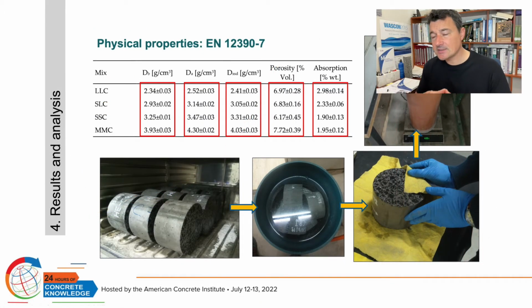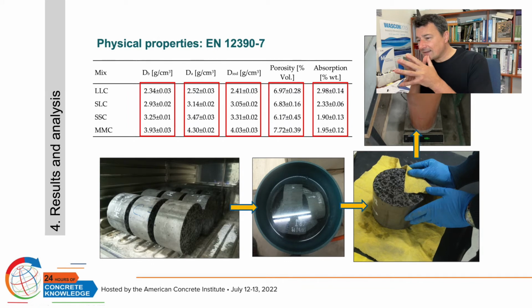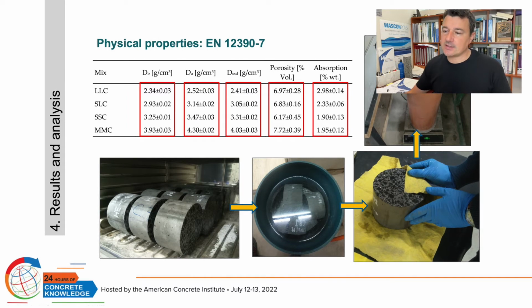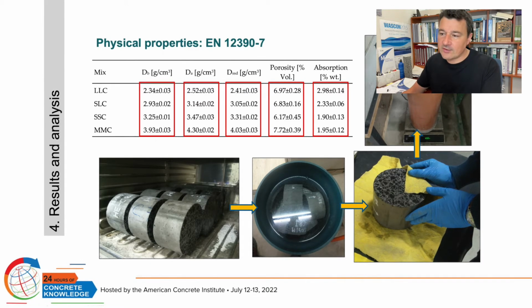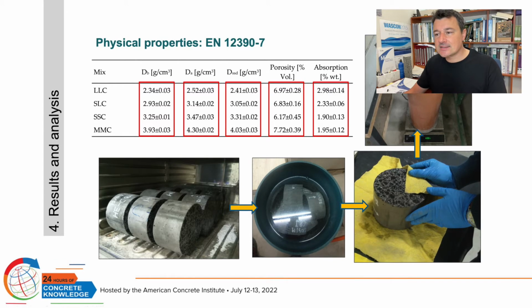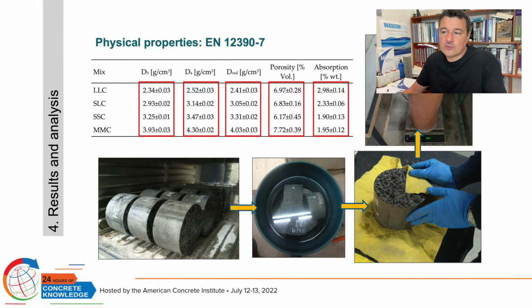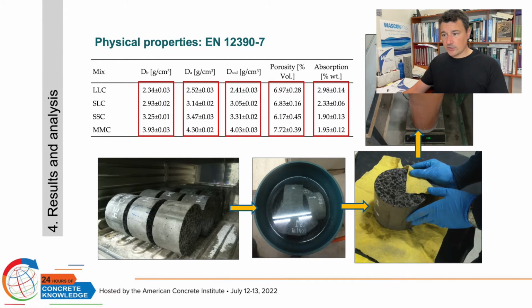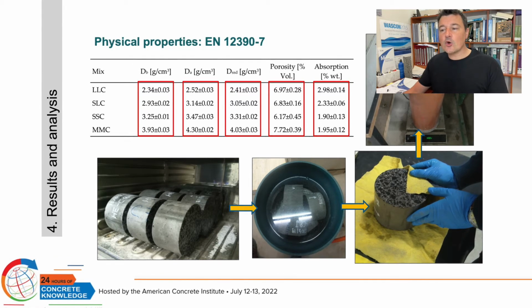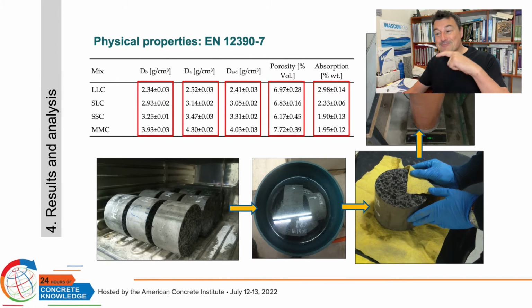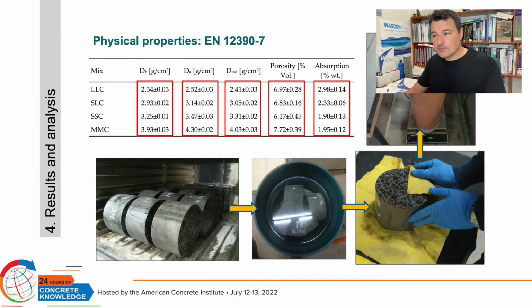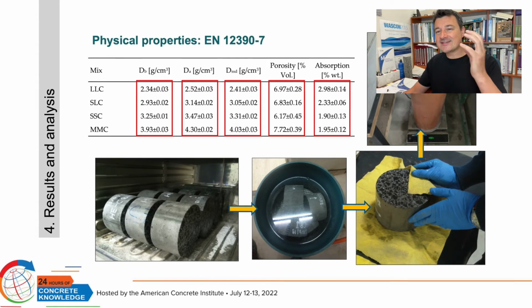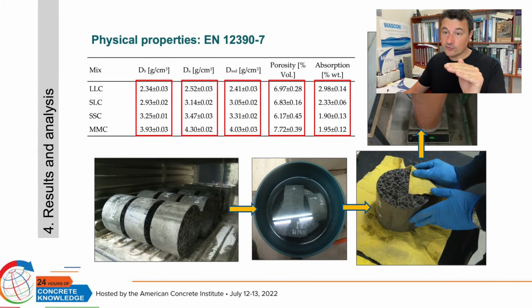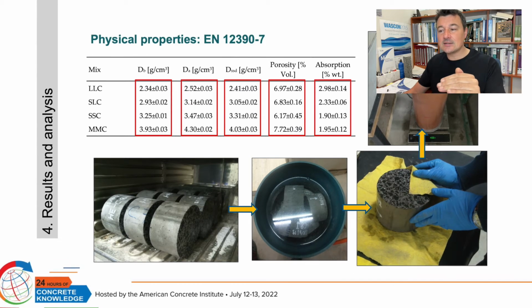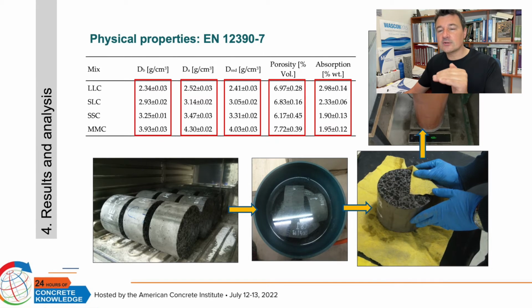Here, the physical properties of the material are presented. What are the densities of the different materials? The density of the standard concrete is around 2.3 to 2.5, depending on the density that we analyze. This is the apparent density, and 2.5 grams per cubic centimeter is the typical value for concrete. But in the case in which we incorporate siderurgical aggregate to the concrete in the coarse fraction, we can increase the apparent density to 3.14.